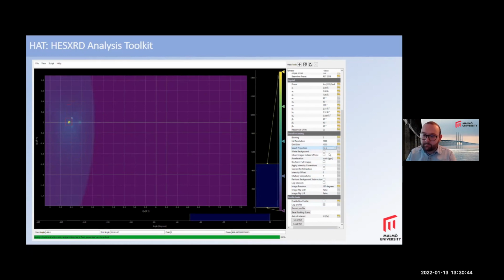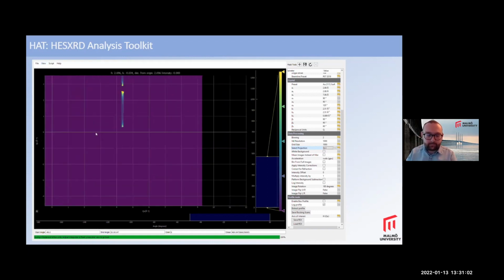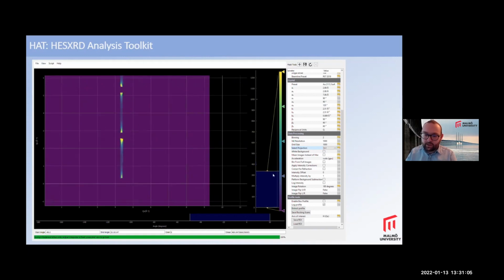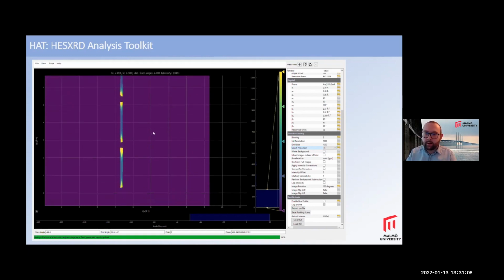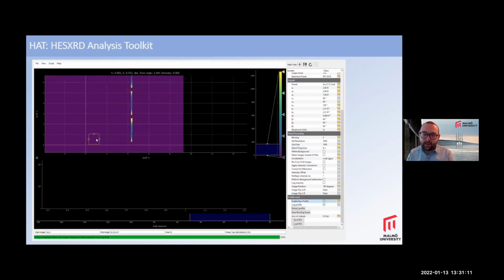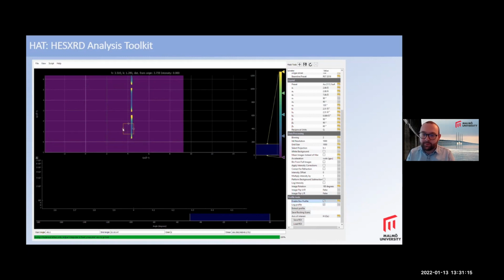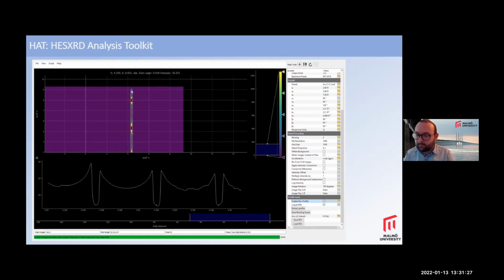So there I'm changing the projection, and then you can change the view and tell it to bin that again, and it will project that onto the HL plane, and you get something that will look like a CTR. It's coming, I think. And then you could take a profile across the CTR and extract the intensity. So this is actually binning every pixel that's in the mask and putting it in a three-dimensional bin. You get something that looks like a CTR. In this case, it really does need to be background subtracted.